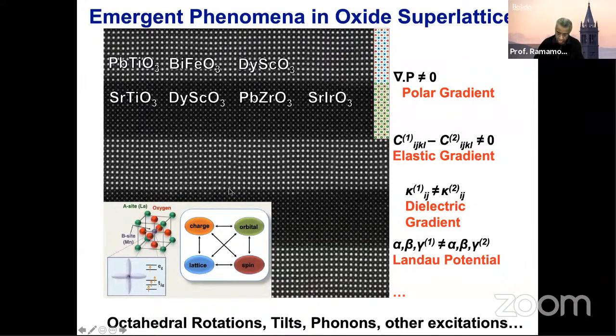And what you see here is basically an atomic resolution image. Each one of these dots is a lead atom. The smaller dot is a titanium atom. Each one of these dots is a strontium atom, and these dots are titanium atoms. So we can use the power of heteroepitaxy, I'll get to that in the next slide, and start to create these artificial structures. I can put polar gradient, elastic gradients, dielectric gradient, gradient in the Landau potential. I can put gradients in octahedral tilts and rotations. It can get very exotic.